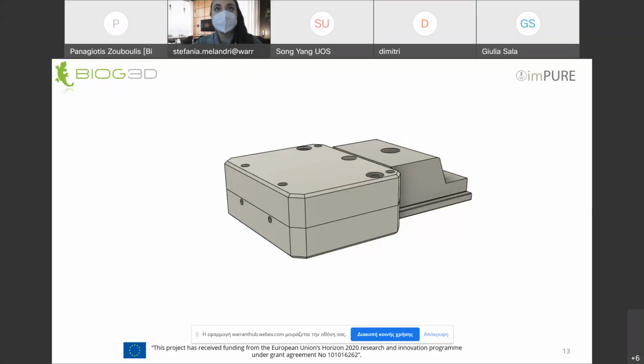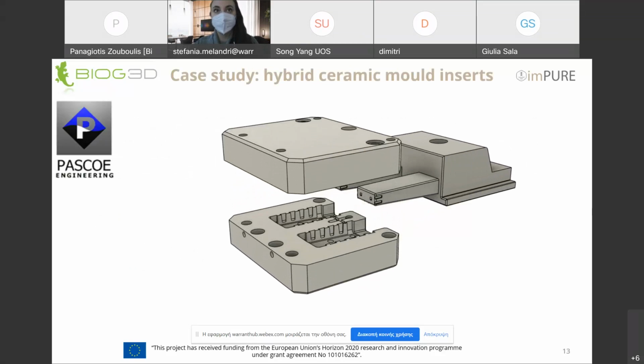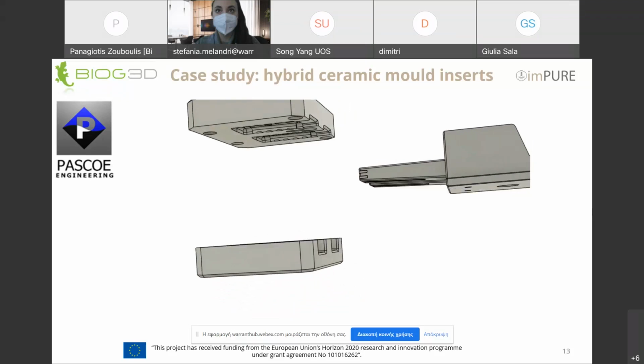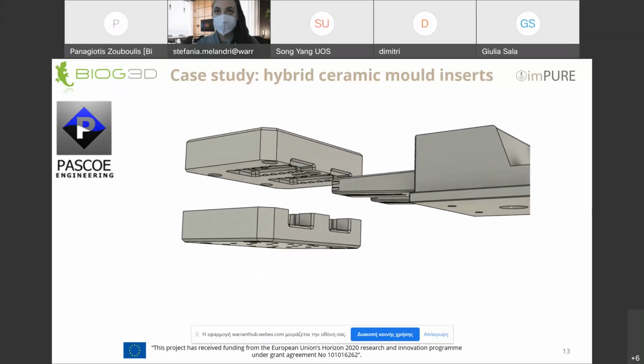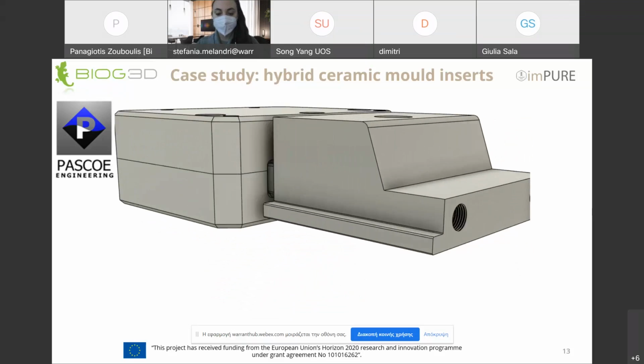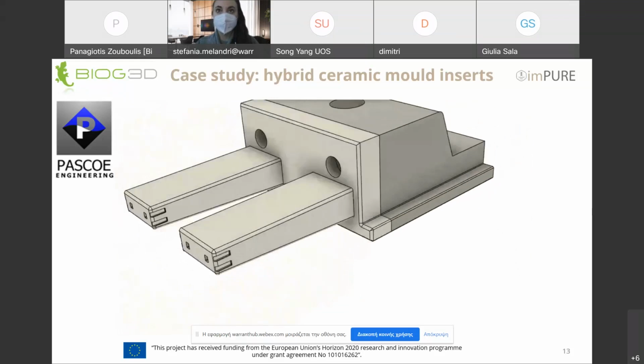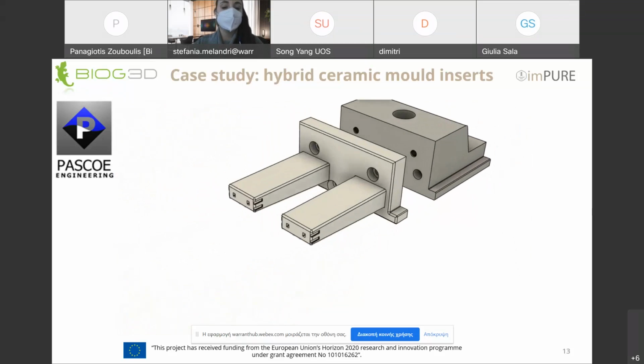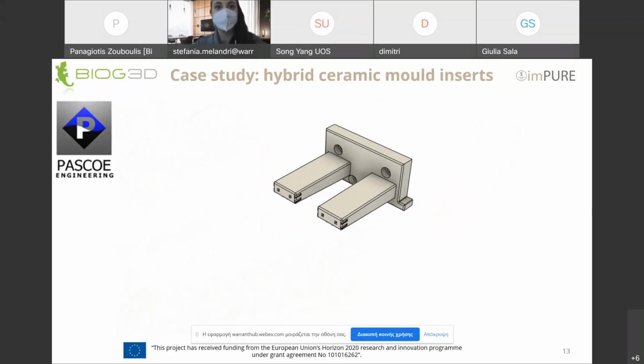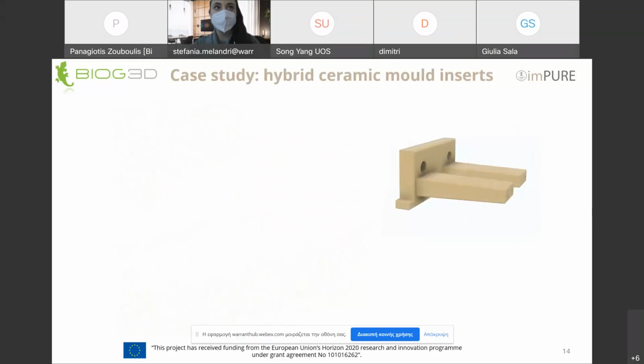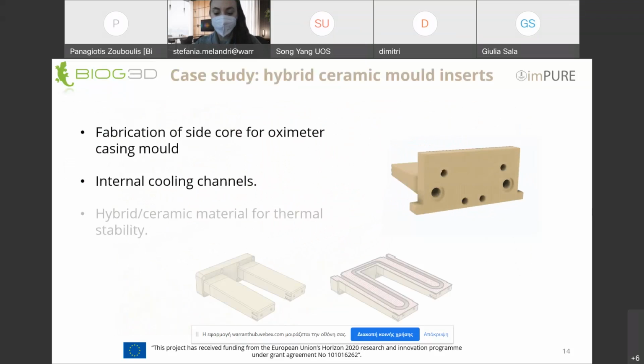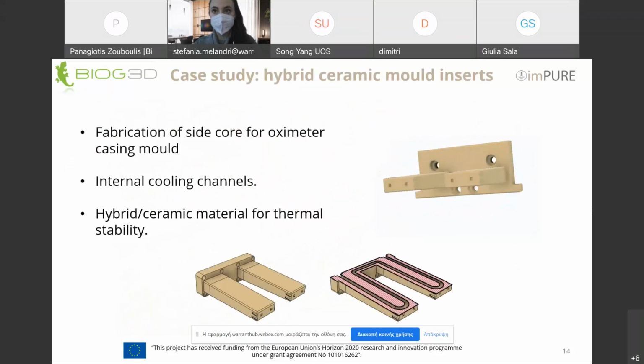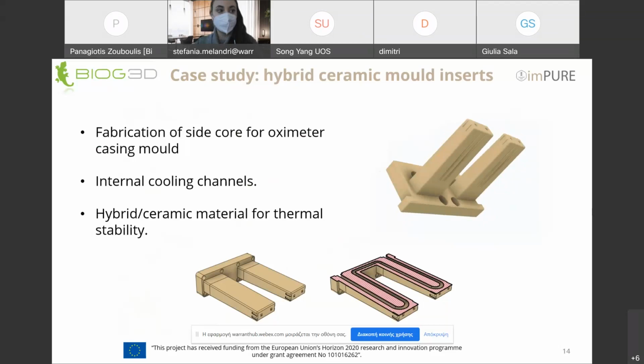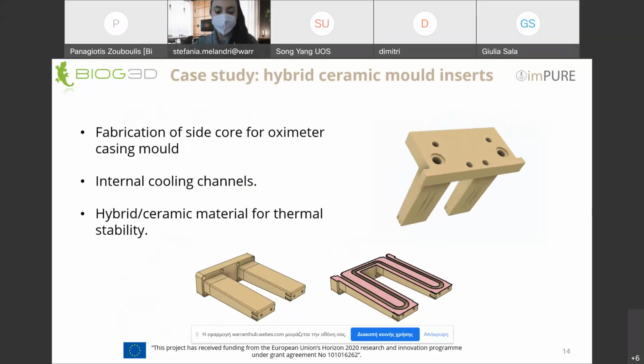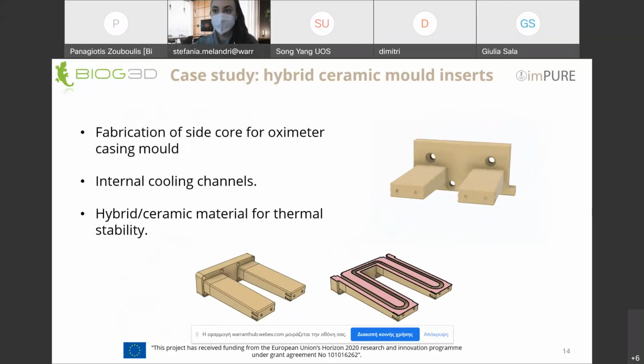Allow me to show you a small animation. This is the design of a part of the oximeter mold designed by Pascoe. As you can see, we have two parts that form the cavity, the casing of the oximeter, and a side core that slides horizontally into the mold in order to produce the internal configuration. So we take this part, the twin side core insert, and we are to fabricate it using a hybrid ceramic material that exhibits high thermal stability and very good thermal qualities, that has also by design internal cooling channels. You can see here the component animated.